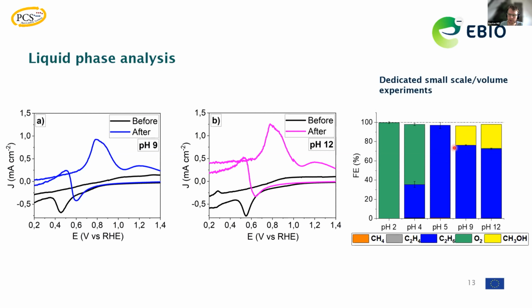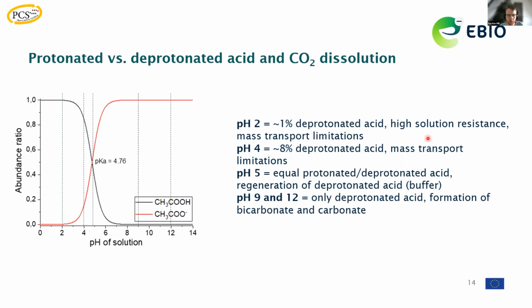But what hasn't been shown so far is that there is also initially a quite selective process for the Kolbe process. And we believe if you would operate this in a kind of divided continuous flow reactor cell, we actually would be able to, even at high pH, maintain a high Faradaic efficiency to the Kolbe process. But we were quite intrigued, of course, what is happening and why are we changing the selectivity from Kolbe to non-Kolbe processes.